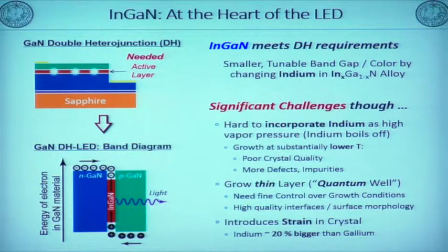But for the active layer, people had worked for a long time to make a high quality active layer. In the 70s and 80s, nobody could make the active layer material. The active layer material should be indium gallium nitride. If we can make very good quality indium gallium nitride, we can make a double heterostructure. But indium nitride growth was very, very difficult in the 80s and 70s. Several groups tried to grow indium nitride, but all failed.